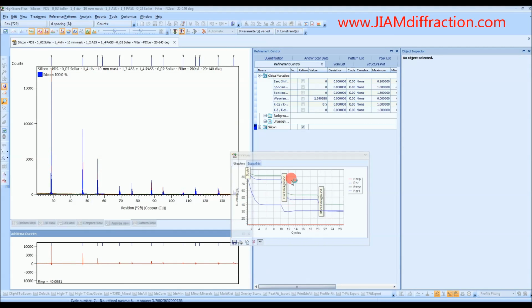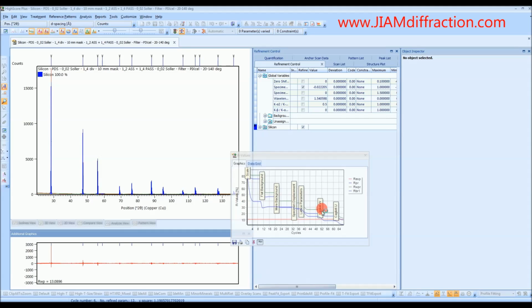And we see the refinement steps that it's going through and how it's changing these R values, which are goodness of fit values essentially. So we see that it modified some of the background terms, the lattice parameters, the profile variables. And as we watch, this difference profile gets better and better, and this RWP continues to improve. So we'll just let it do its thing. It's almost done.